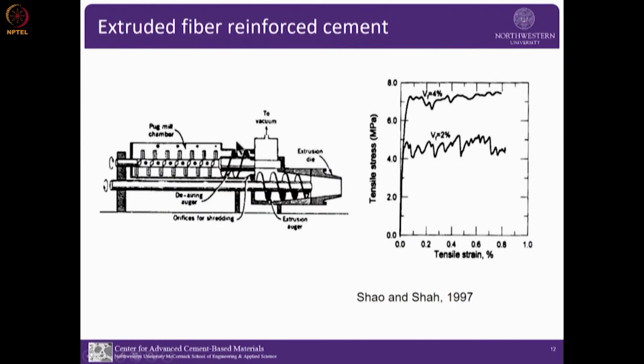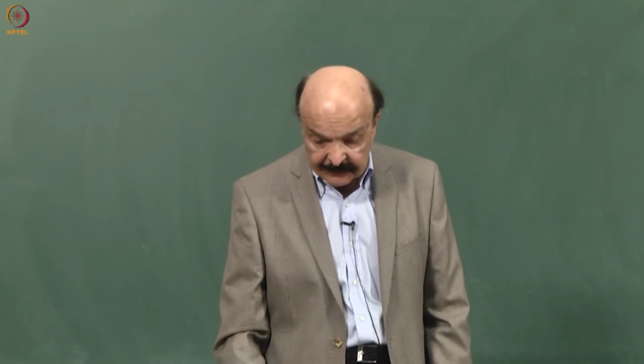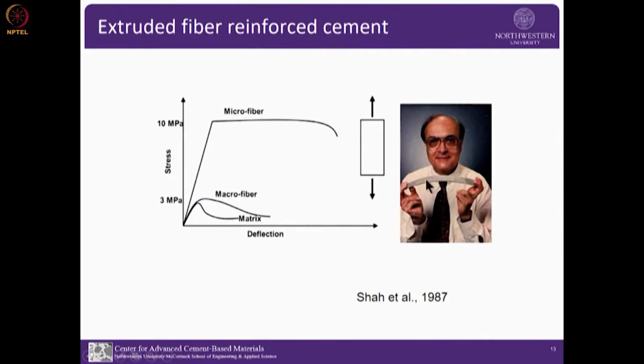And you can see that we got 2% and 4%. We got a higher tensile strength because fibers can now interact with micro cracks. And if you design it right, you get a strain hardening response, because it's essentially like a ductile material. To show that, I often during that time showed this to my class. As you can see from the hair, it was a long time ago, 1987. But this is currently where we are in fiber reinforced composite.